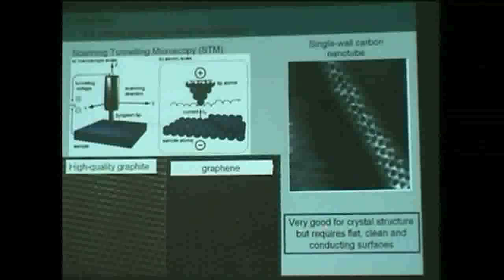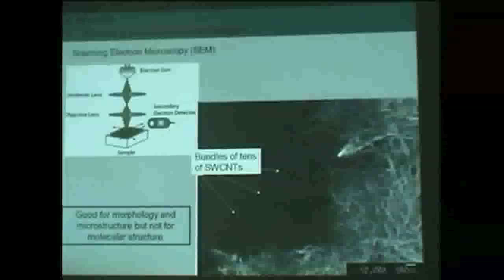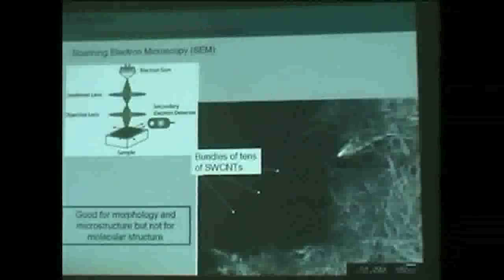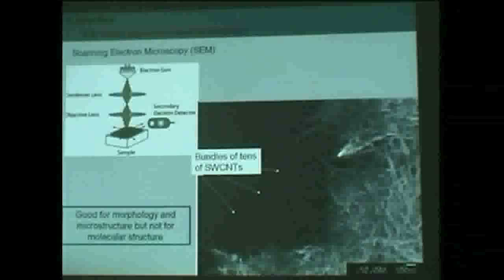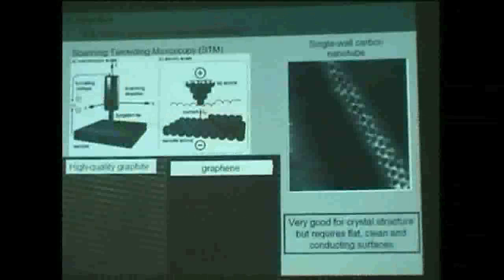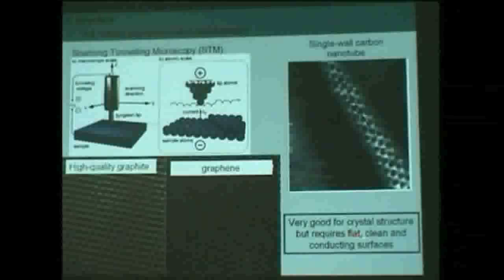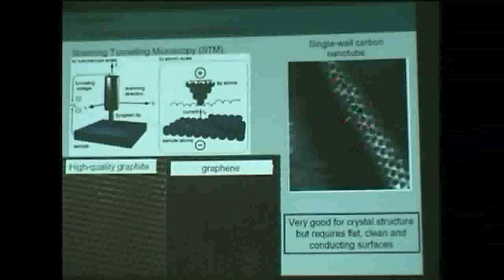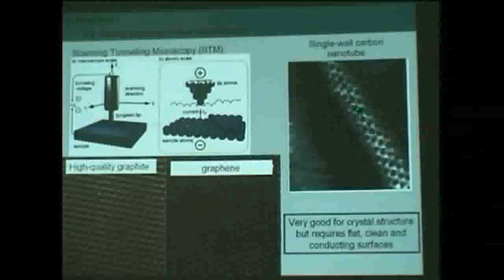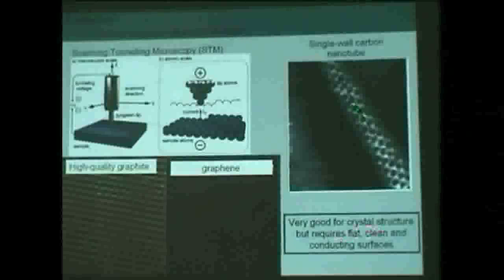If you use a sample that isn't flat, you will get nothing by STM. You need something which is already very flat, so you need a flat sample preparation. You need it to be very clean, because if you have contamination by air molecules, water, CO2, or anything else, it will be very difficult to see these atomic details. So you need a very clean surface.